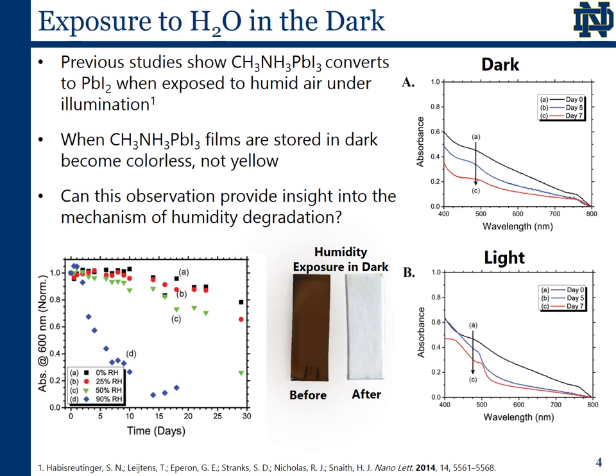Therefore, we studied the degradation of methyl ammonium lead iodide films in the dark in hopes that this would provide information as to the mechanism of humidity degradation. We tracked the degradation of the methyl ammonium iodide films stored at a range of relative humidity conditions, first by UV visible absorption spectroscopy in order to determine the rate of this decay process.